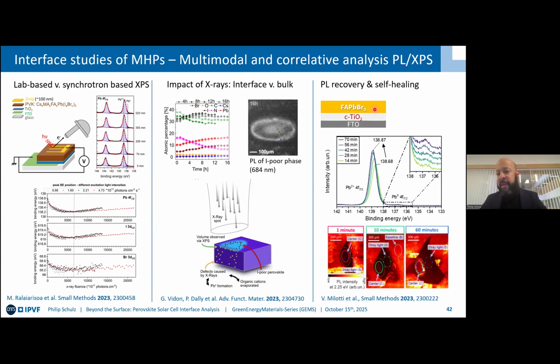And moving on now to this last example, we'll use formamidinium lead bromide. Here again, measured at the synchrotron with high intensity radiation. You can see how the lead peak is actually growing as you're losing the more volatile formamidinium and bromine from the surface. You're forming metallic lead.